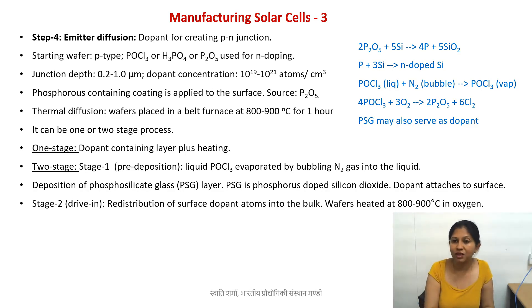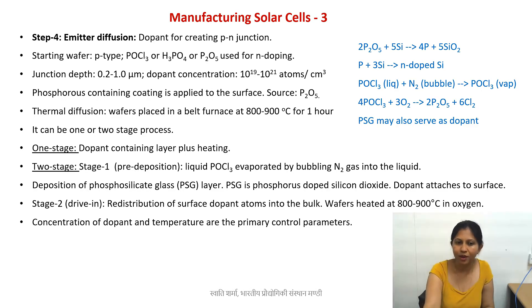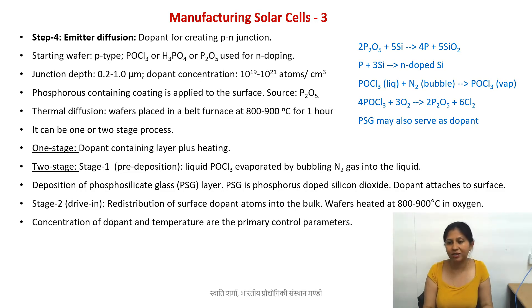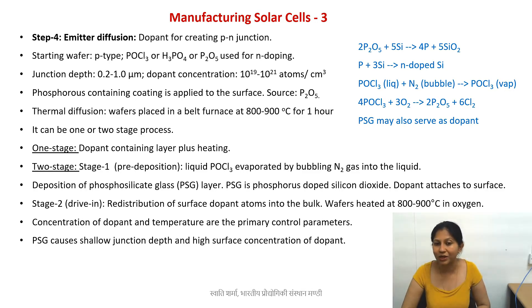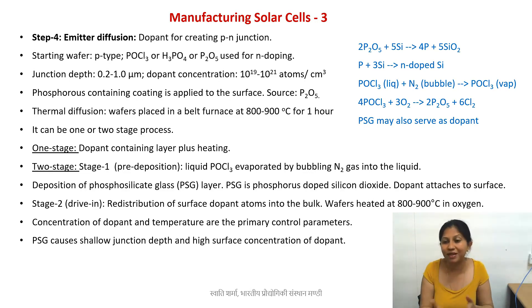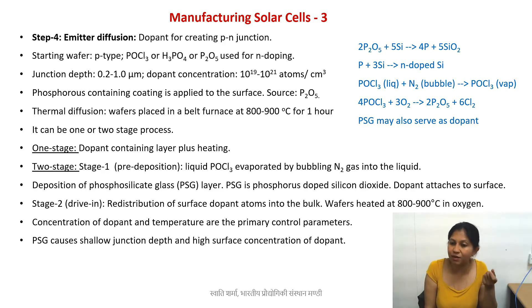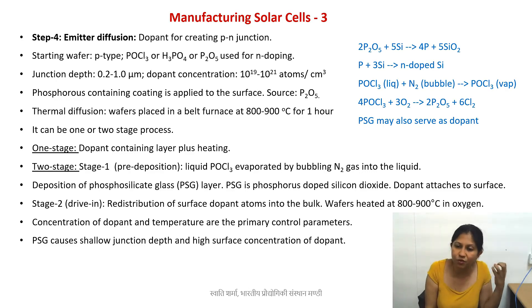As mentioned, the phosphosilicate glass may also act as a dopant. To control this process, you can control two primary parameters: temperature and concentration of the dopant. The phosphosilicate glass was a useful byproduct, but we also need to get rid of it at some point. When you have PSG (phosphosilicate glass), it causes a shallow junction depth but higher surface concentration of the dopant. You have to decide whether you want it or not, but after doping you want to remove the PSG layer.